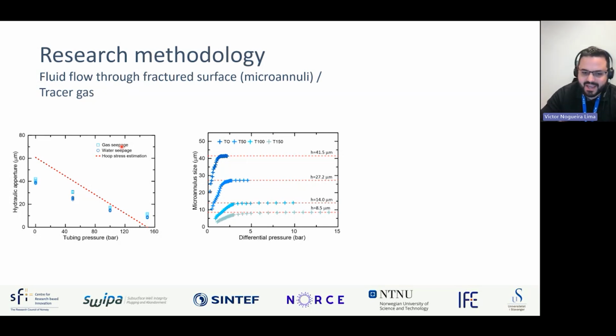Then we can see what Nils also talked about: at that point, we do not have the direct microannulus size that we measured before in the single phase measurements, but an effective microannulus size. As we increase the gas pressure, we tend to this asymptote, and then we reach the actual or real microannulus size, which is the one that we measured in the single phase measurements.